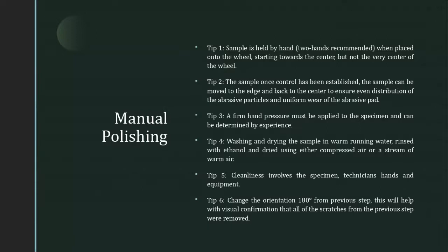Believe it or not, it's going to be the control of the sample more than the pressure applied to the sample that gives you the best results. If you cannot place the mount on the disc without the sample wanting to fly out of your hand, you'll never want to polish again. So one of the best things to do is hold the sample with two hands, and I'll demonstrate that in the labs.